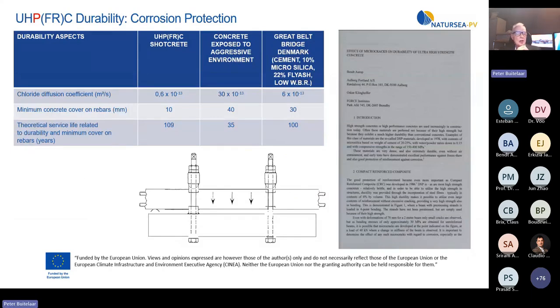Corrosion of fibers and/or reinforcement in UHPC has been investigated by Aalborg Portland researchers and test institutes since the early 1980s as part of the durability performance. While first corrosion tests were done on unloaded specimens, later research as part of a Eureka and a Brite project focused on highly loaded specimens to simulate the behavior of real-life structures and exposed them to wet drying cycles with salt water and dry air. Also, UHPC shotcrete shows in 10 mm layers a very low chloride diffusion coefficient.